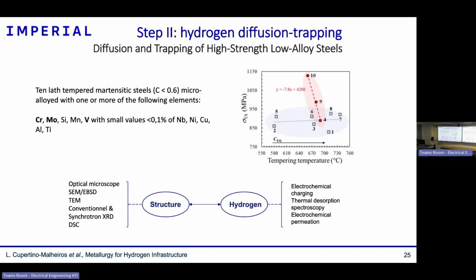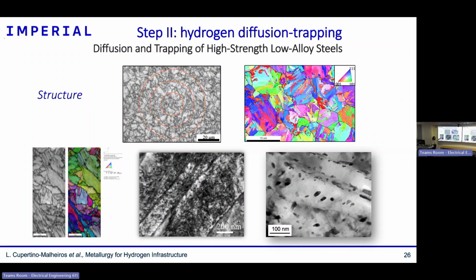In this work we first compare what you get in terms of hydrogen diffusion and trapping behavior for all of those steels. I ran experiments that characterize the structure of these steels and link it with the hydrogen behavior, basically how fast hydrogen diffuses and moves inside of those steels. The structure of these steels looks more or less like that. What we are interested in here is the defects of these structures, the trap sites where hydrogen can accumulate and maybe eventually cause fracture.